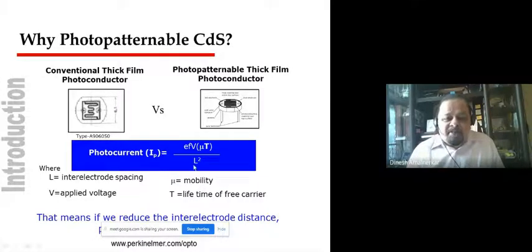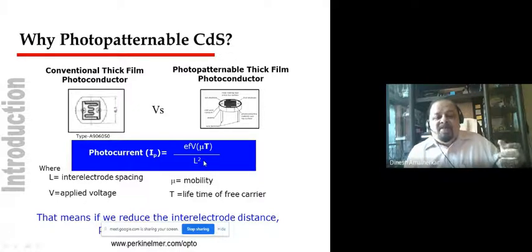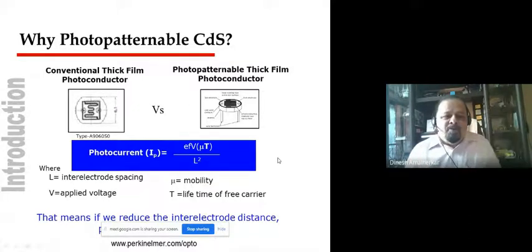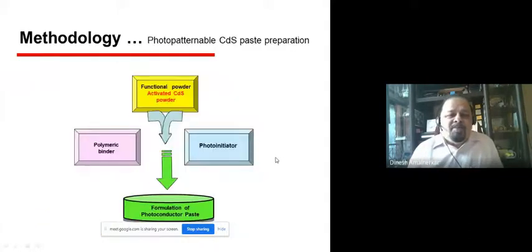Let me repeat again. The whole idea here is to reduce the interelectrode distance from maybe half a millimeter to 100 micron, as a result of which photocurrent can increase inversely with the square of the interelectrode distance. That was the idea of switching over to photopatterning of cadmium sulfide. Now, how do we prepare the photopatternable cadmium sulfide paste?